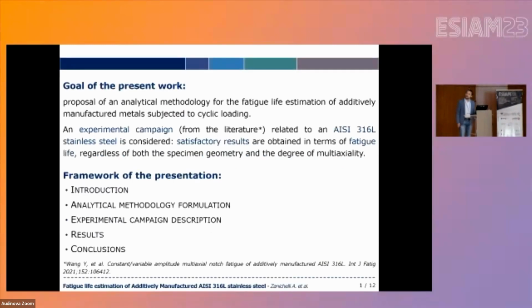The present research work deals with the proposal of an analytical methodology for the fatigue life estimation of additively manufactured metals, which are subjected to cyclic loading. In particular, an experimental campaign taken from the literature is considered, and satisfactory results are obtained in terms of fatigue life, regardless of both the specimen geometry and the degree of multi-axiality.